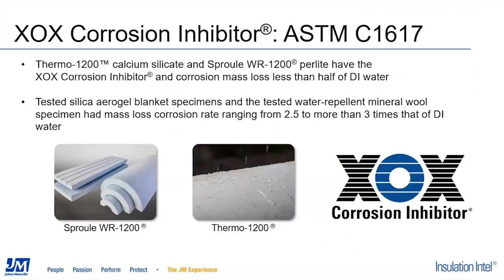So you can see from this data that products containing the XOX corrosion inhibitor, that being the Thermo 1200 calcium silicate and the Sproule perlite, have a mass loss corrosion rate that's less than half of that of DI water, so excellent performance in helping to prevent and delay the opportunity for corrosion to occur, whereas the silica aerogel and water-resistant mineral wool products all had mass loss corrosion rate ratios significantly higher than that of the DI water, demonstrating that those products all did introduce additional compounds or chemicals into the system that could contribute to an accelerated rate of corrosion.